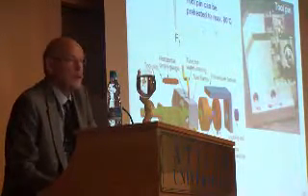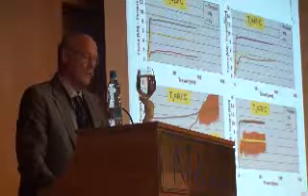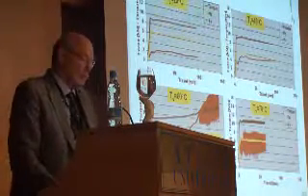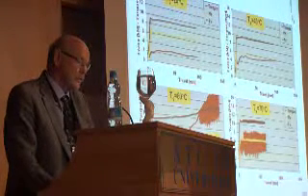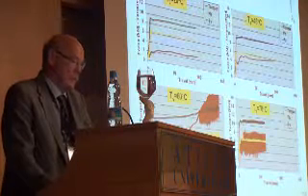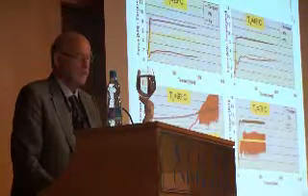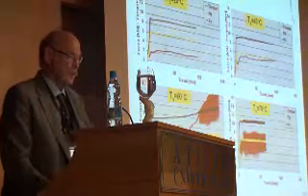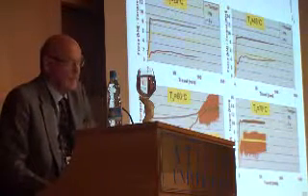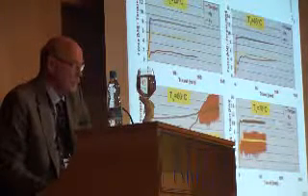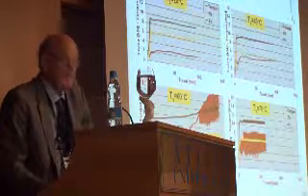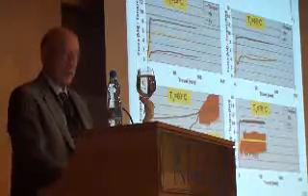We can preheat the tool pin to simulate the conditions in the production tool in deep drawing, typically up to 80 degrees. And here you see the influence of the temperature of the tool on, we have the front tension force here, the back tension force, which is constant, and then the torque, which is proportional to the friction. Testing stainless steel with plain mineral oil with no additives goes very well at 20 degrees. At 45 degrees the torque increased, but it's still working fine. But heating to 60 degrees you will see increasing torque and stick slip due to galling. At 70 degrees the lubricant breaks down immediately.